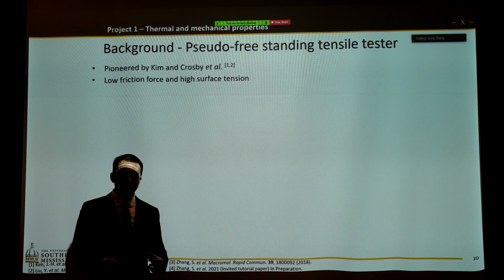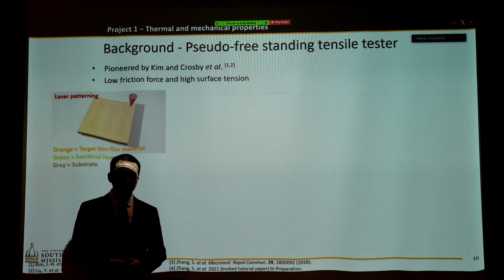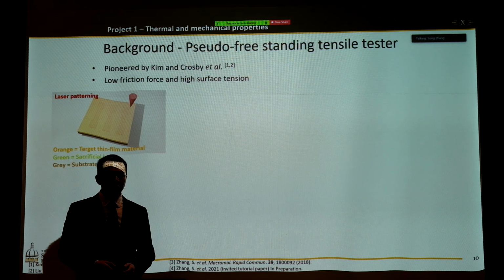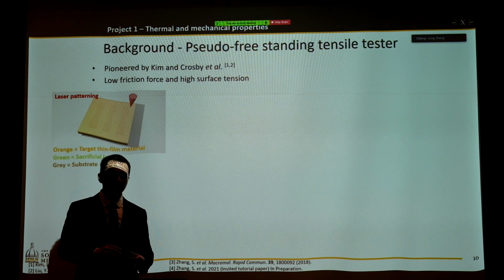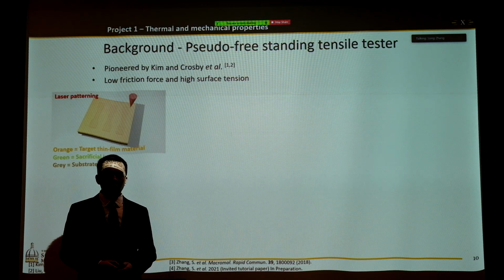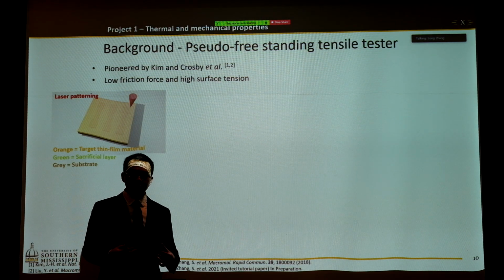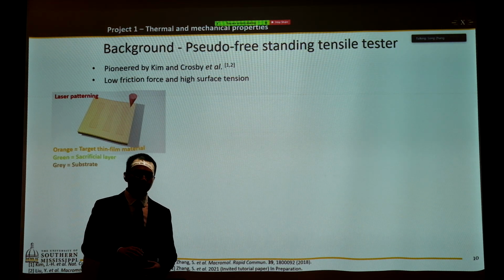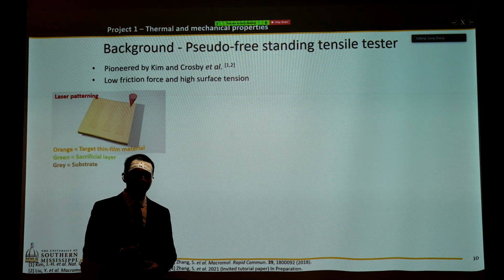Okay, now how do we tackle the first challenge? We developed this pseudo-free-standing tensile tester, and the fabrication steps of the film are as follows. We first establish a two-layer polymer film on top of the substrate, where the first layer is a water-soluble layer, also called a sacrificial layer. And on top of that, we have the thin film we want to measure.